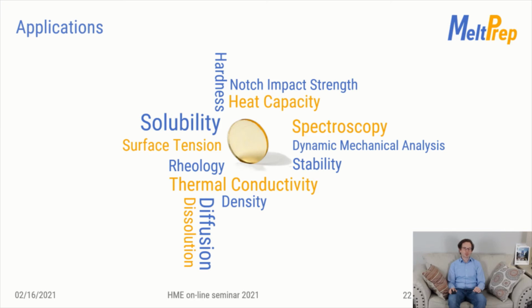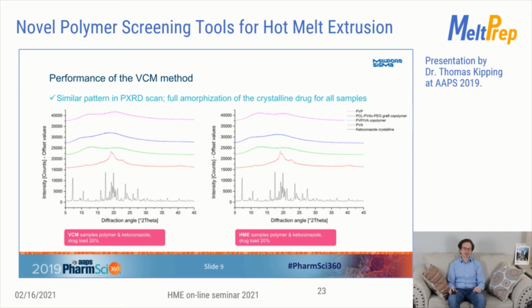I want to start with one of the most frequent questions that I receive. Are VCM samples comparable to hot melt extrusion? At the AAPS in 2019, Thomas Kipping from Merck Germany, also known as MilliporeSigma in the US, demonstrated exactly that. They compared analytical results from VCM samples to hot melt extruded samples. I would like to highlight one part of their studies, the XRD scans. If you compare the left graph with the right graph, you barely see a difference. That means VCM is also yielding an extrusion-like result in terms of XRD data.